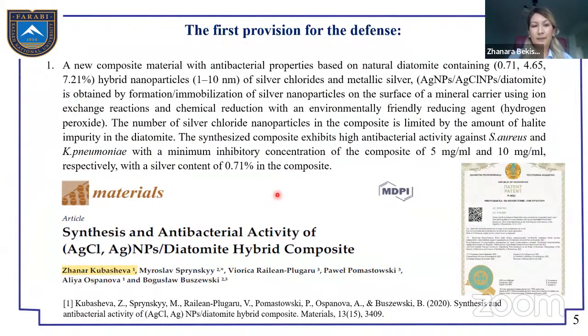The first provision for the defense: a new composite material with antibacterial properties based on natural diatomite, containing 0.71, 4.65, and 7.21% of hybrid nanoparticles of silver chloride and metallic silver with size from 1 to 10 nanometers, can be obtained by immobilization or formation of silver nanoparticles on the surface with an ion exchange reaction and chemical reduction with the reducing agent hydrogen peroxide. The amount of silver chloride nanoparticles can be limited by the impurity of halides in the natural diatomite. The synthesized composites show a high antibacterial efficiency against Staphylococcus aureus and Klebsiella pneumonia with minimum inhibitory concentration of 5 and 10 milligrams per milliliter respectively, with a content of 0.71% of the composite.